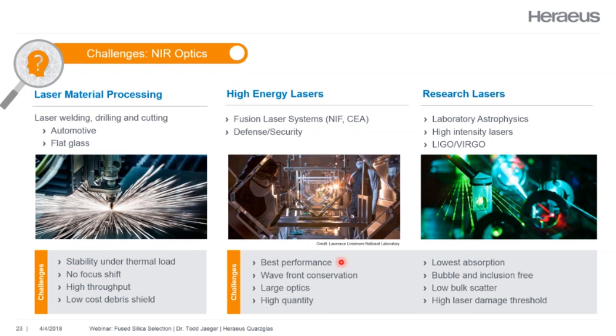If you think about the laser fusion facilities, you're focusing nearly 200 beams onto a spot that's about the size of a pinhead. And of course, if you have any variation in your wavefront, your focus isn't going to be where you need it to be. They need very large optics, and they need these optics in high quantity. And of course, lowest absorption, bubble and inclusion free so that we don't have damage from that, low bulk scatter, and very high laser damage threshold of the material itself.